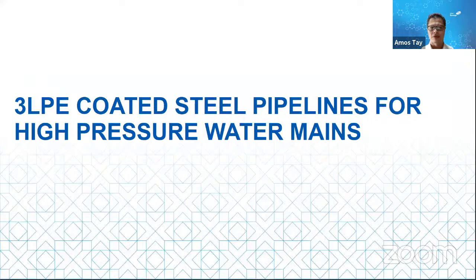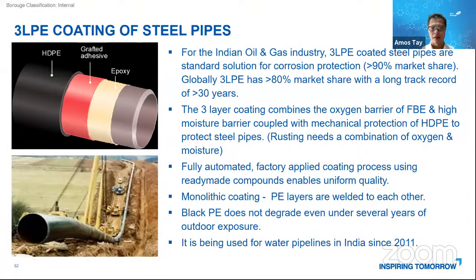Borouge also highlights 3LPE, 3-layer PE coated steel pipe for high pressure water mains. PE pipe can only withstand certain pressure, and if you have exceeded the pressure, there's no way a PE pipe can be used. So a steel pipe can be used to transport water at higher pressure. Let's look at this PE. You see the picture is a 3-layer HDPE: top layer, then the adhesive layer, then epoxy, and then the steel. So this is 3-layer PE.